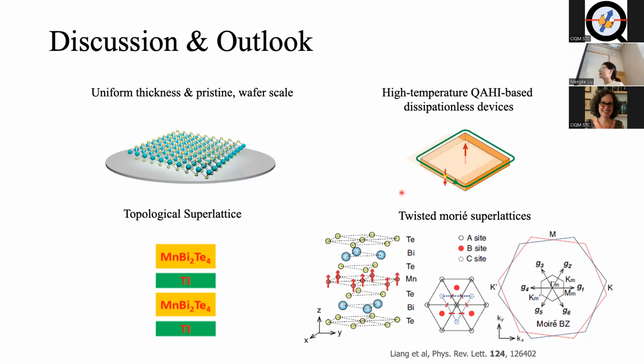And I have skipped a little bit on the topological superlattices. Actually, from the coupled Dirac model calculation, we predicted that the topological superlattices can have different combinations of MBT and BT or BS, bismuth telluride or bismuth selenide. They can form different topological phases. They can form either Weyl semimetal or just trivial insulator by stacking them in different order and in different ratio, like 1:1, 1 MBT, 1 BT, or 1 MBT, 2 BT, and so on and so forth.